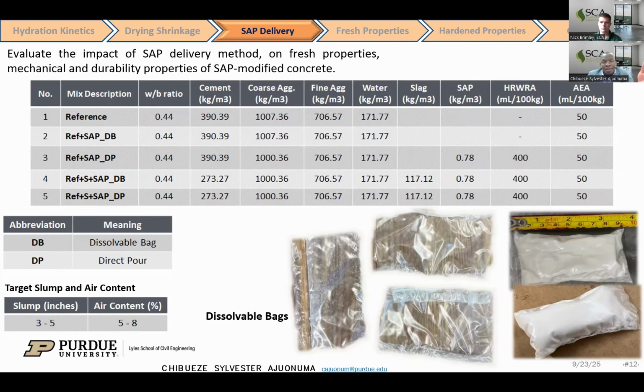So we had the reference mix, and then we had the 2 delivery methods where we added the SAP using the dissolvable bag, and secondly, we directly poured the SAP into the concrete mixture. We did this for the reference mixture where we just added SAP, and then also 30% cement replacement using slag, in which we also added the SAP directly, and then also DB, we also added using the dissolvable bag. Our target slump was between 3 to 5 inches, and then the air content was 5 to 8%.